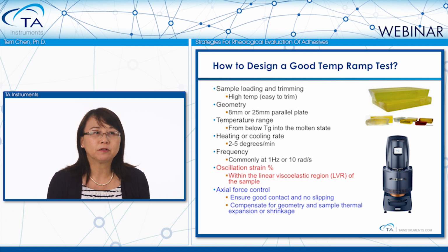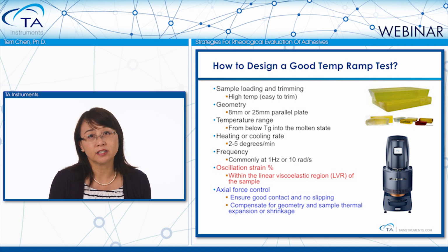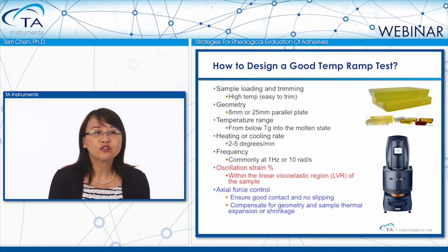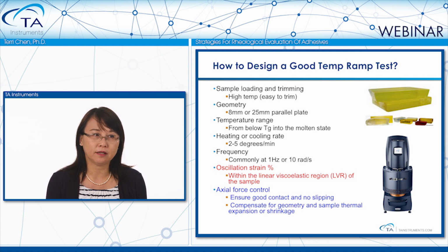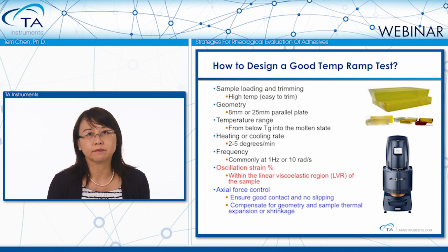The most challenging parameter setup is the sample strain. Strain needs to be within the linear viscoelastic region of the sample. When a sample undergoes such a big change in physical property, it is important to have the capability of adjusting the strain during a temperature ramp experiment.